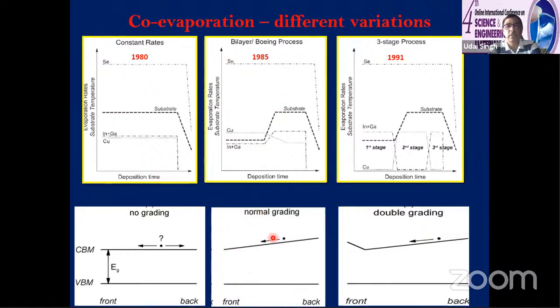Selenium is always there. And in 1991, NREL gave a 3-stage process, which has given the highest efficiency, which is basically the double grading. In the first stage, there is no copper. They deposit only the indium gallium, and then they reduce the indium gallium to 0 and increase the copper. In the second stage, only copper they deposit. In the third stage, again, they reduce the copper and increase the indium gallium. So it gives a double grading. This has given the highest efficiency, and most of the people are following this.